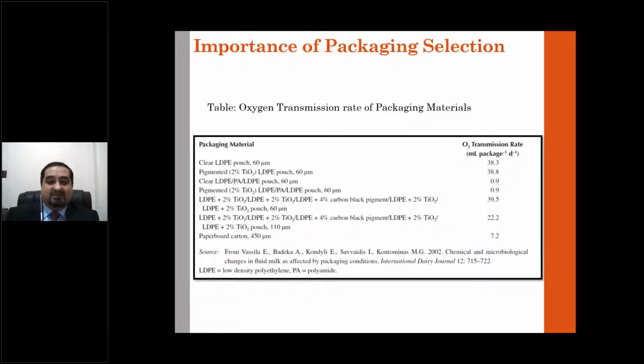You can see this table in which a clear LDPE pouch has an oxygen transmission rate of 38.3. Now that value would reduce quite a lot. From 38.3, we will move to 0.9 for clear LDPE that has polyamide or nylon present in between the LDPE layers, along with the tie layers. Obviously, the tie layers are going to be there, but that enhancement in the overall barrier properties of LDPE is why we move towards multi-material based multi-layer structures.